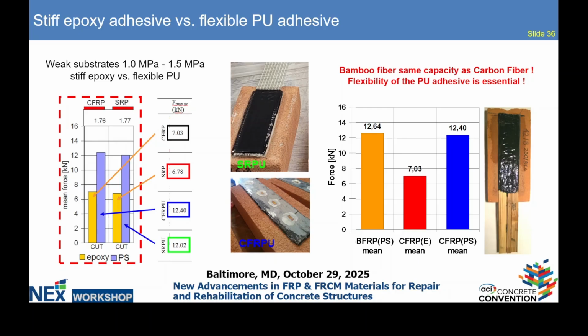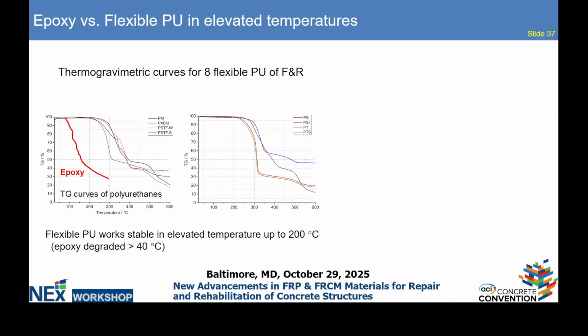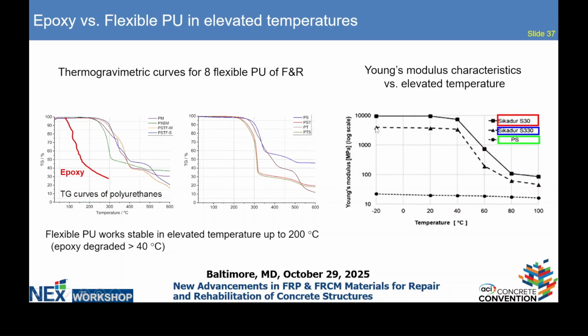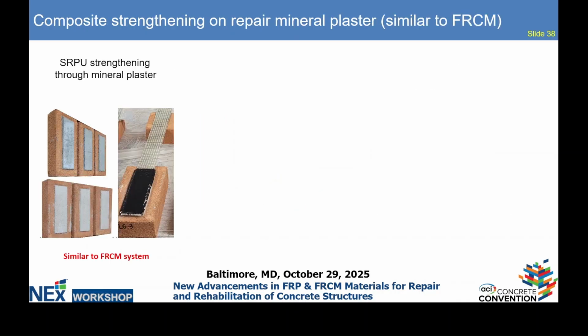So the adhesive is the critical and crucial point here. Also, when we compare epoxy with polyurethanes, polyurethanes are stable up to 200 degrees Celsius at elevated temperature, whereas epoxy is losing its properties. It is presented here according to Young's modulus. This curve is stable with polyurethane, and the two composites with epoxies lose their properties at elevated temperatures.